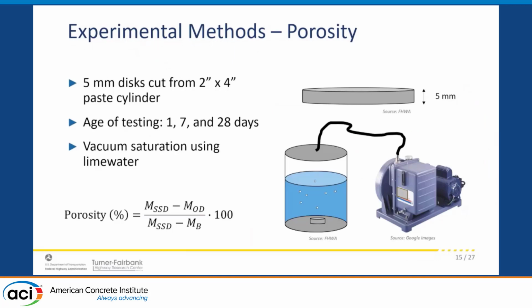Because we wanted to verify if we could relate the resistivity to microstructural features, we actually tested the overall porosity of our systems. To do that, we cut the paste specimens into pretty thin discs, about 5 millimeters thick, and then we vacuum saturate them.